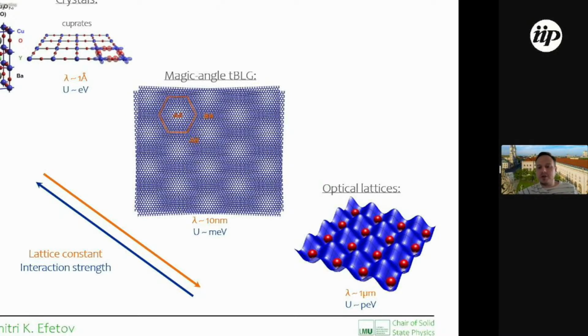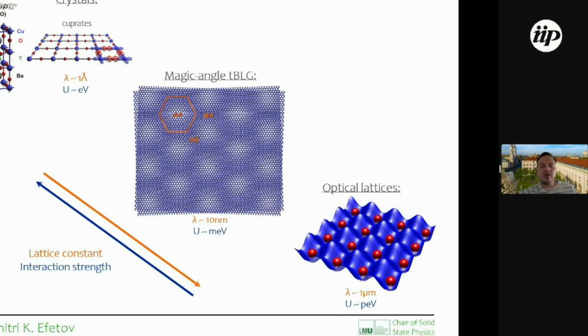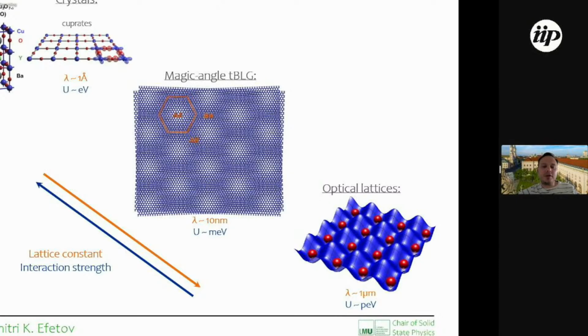The distances here are in the order of micrometers, and therefore interaction energies are also extremely weak, in pico-electron volts, and you need to cool these systems down to nanokelvin to even observe anything. And so Moiré materials like magic angle graphene occupy a sweet spot between the two. Here, the length scales are in the order of 10 nanometers, and the interaction energies are therefore in